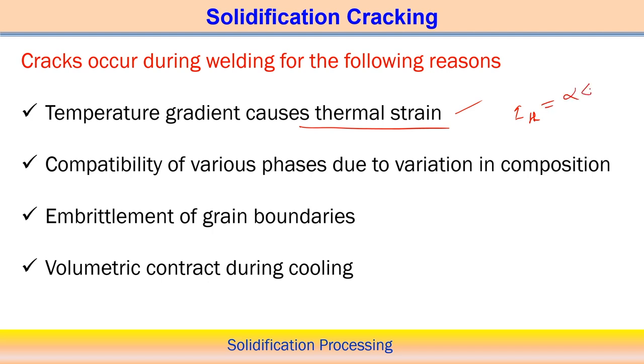Thermal strain is the coefficient of thermal expansion times delta T. The coefficient of thermal expansion, we know, is the change of length per unit degree of temperature, and the temperature difference is what induces the thermal strain. So if the thermal strain is too high and exceeds the critical value, then we can expect some cracking due to the presence of the temperature gradient. Although we are using the temperature difference here, we call it the temperature gradient because it takes care of the spatial difference: in one particular space, what is the difference of the temperature. So the temperature gradient is one of the important parameters.